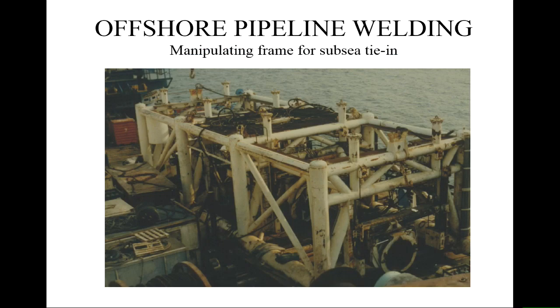So this might be a sort of system that you've got on the deck. The pipes would end up in here and in the other side, and they're all clamped together and held in place, so you can then do the welding by this process. And if the clamping is high enough, you can lift the pipeline up and, as I say, weld at atmospheric pressure. Or you can have a system that just aligns the chamber, which then goes down over the top of the system. So just because there's a chamber, it doesn't mean that's the only piece of equipment that you need to do the welding.